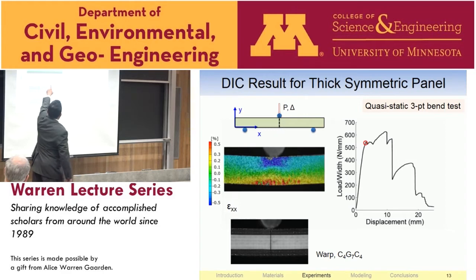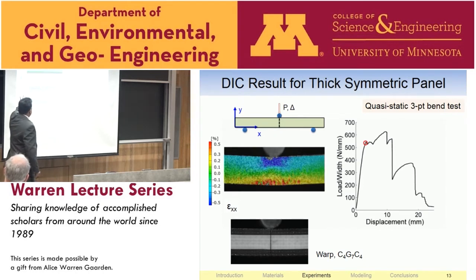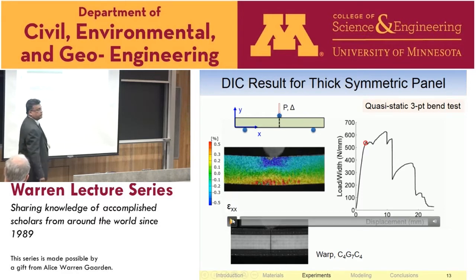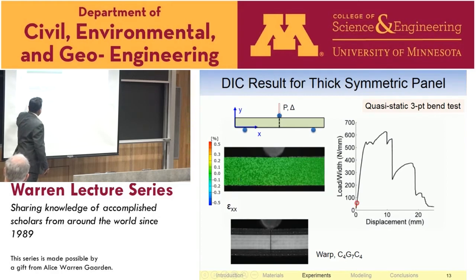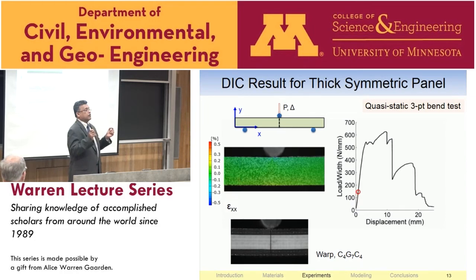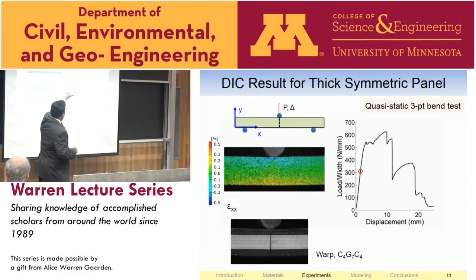What I wanted to show you was how the progression of failure develops as we 3-point bend the structure. And then I want to show you one without the speckled images, how it fails. I can describe it. It linearly responds, and the tensile side of the specimen starts to show cracking. But the cracks are not allowed to grow. So the cracks occur, producing some ductility, right? And then that final collapse is when the top carbon layers fail in kinking.